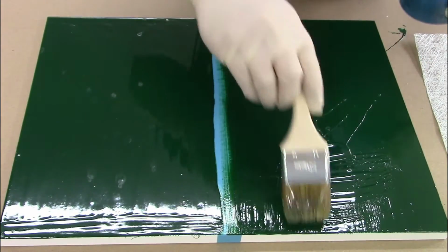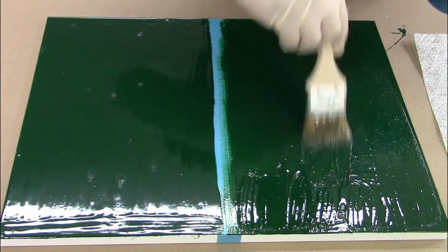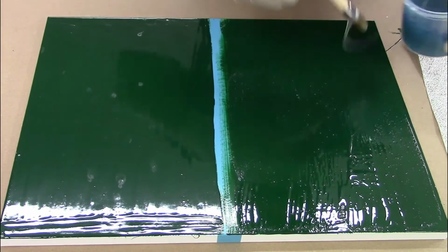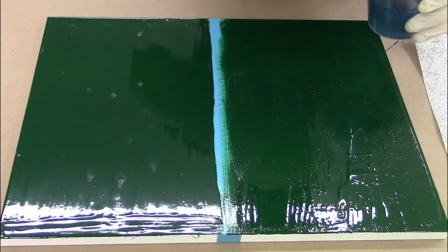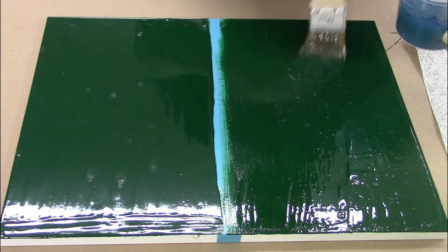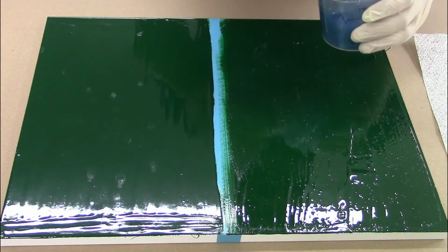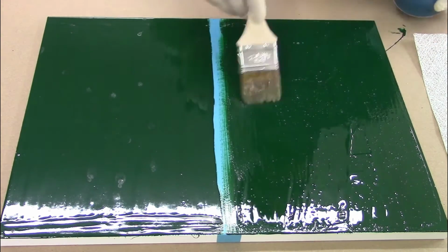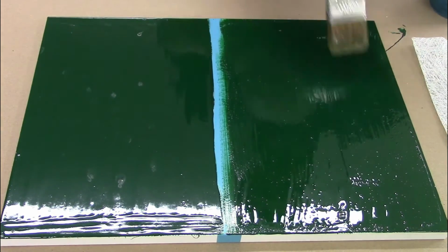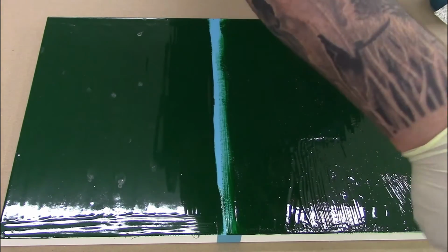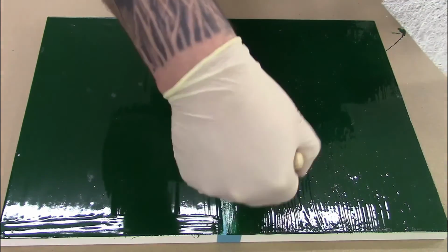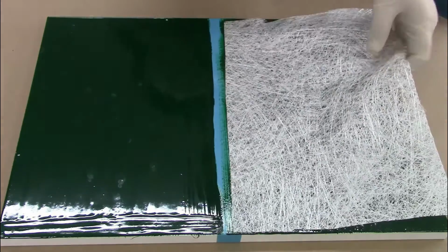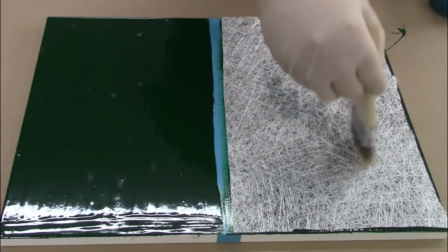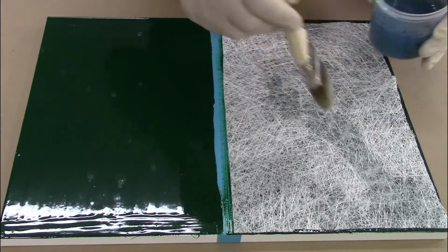When you apply the resin and matting to the Gelcoat, you should also have a good working temperature of the same 15 to 20 degrees C, and also the average dosage of 2% catalyst to your resin. Here, on the right side of our test panel, we're using a polyester resin with only 1% catalyst added, and applied in a very cold working environment, so that the resin will cure very slowly.